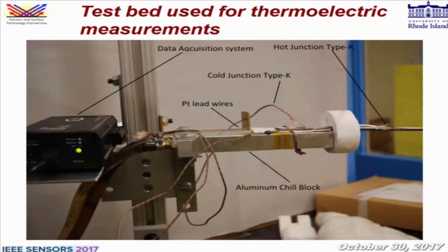So this is the setup that we use for testing. We have an aluminum chill block shown here. We feed water or ethylene glycol through in order to keep it at as low a temperature as possible. On it, we have our sensor. One end of it is cooled on the chill block, the other end is heated.